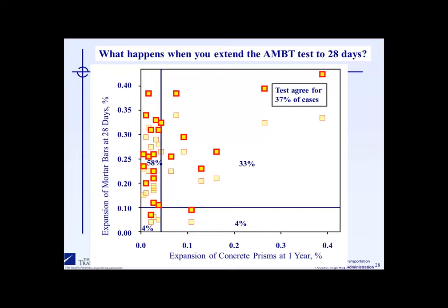What we'll see when we talk about the AASHTO recommended practice is that we recommend that a user of the mortar bar test would first establish a correlation between the concrete prism test and the accelerated mortar bar test. Provided that the correlation is reasonable, that would allow the use of the mortar bar test to evaluate aggregates and also preventive measures.